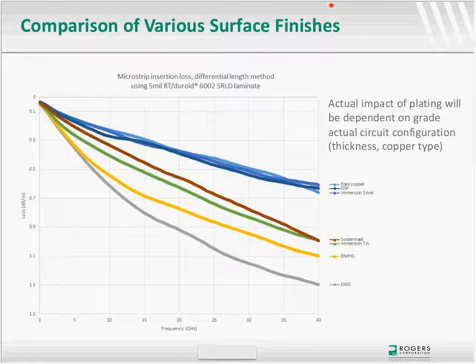Many people typically will just say, give me the lowest loss dielectric, the lowest loss tangent, and I'm just going to go with that. In some cases, that may be a good choice. But in some other cases, we're finding that materials with more balance, a mid-dielectric constant around 3.0, seem to have a better overall balance of electrical and mechanical stability, reliability concerns, and also have good enough losses, particularly when making proper selection of foil and plating. So it is something that one has to take into account, and the medium frequency bands, 27 gigahertz.